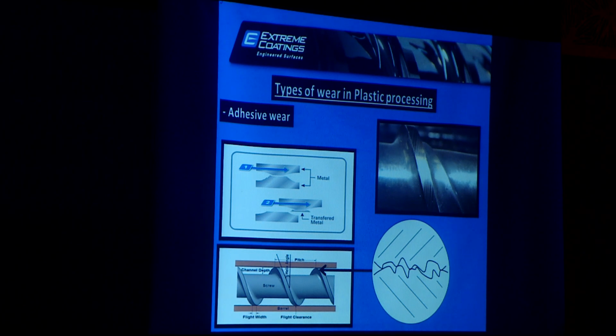The primary reason wear happens is metal to metal wear. Why does metal to metal wear happen? Unfortunately, in extrusion or injection molding machines, the screw assembly is a cantilever assembly. So one side is always going to be free. And if you put fillers, or if the diameter of the screw is very high, because of the self weight, some way, two surfaces are going to come in touch with each other. Which two surfaces? The barrel ID and the screw OD.